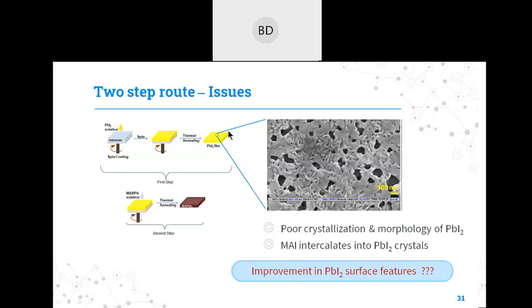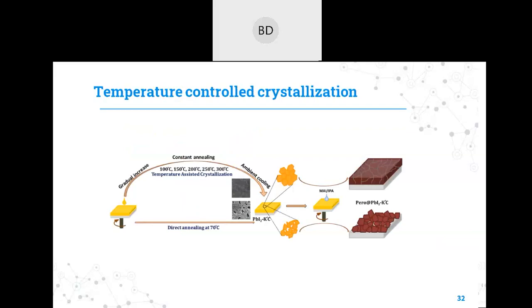So we thought, why don't we improve the PbI2 film structure itself so that we can have a better perovskite phase? In this method, generally we are using a direct annealing process of lead iodide film. We spread the lead iodide film on the substrate and we anneal it at 70 degrees centigrade, which gives a lead iodide film. If you anneal directly, it gives this kind of structure, this kind of crystallization.